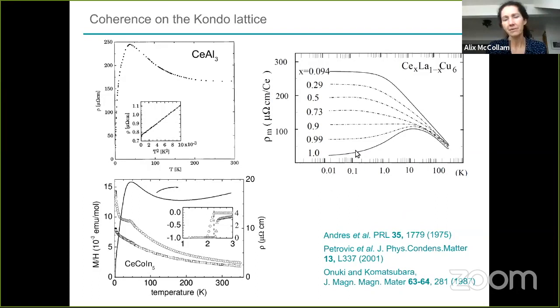This is a nice example. It's a very famous example. This is cerium copper 6 doped with lanthanum. So the cerium copper 6 is this bottom curve. And again, you see this coherence temperature and the resistivity drops at low temperature. As you take away the F electrons, so you dope with lanthanum and you're basically taking out the F electrons, then you spoil this effect. You take away the Kondo lattice and you remove the coherence, and you go towards something that looks a bit more like the single impurity problem. Lower density of moments.